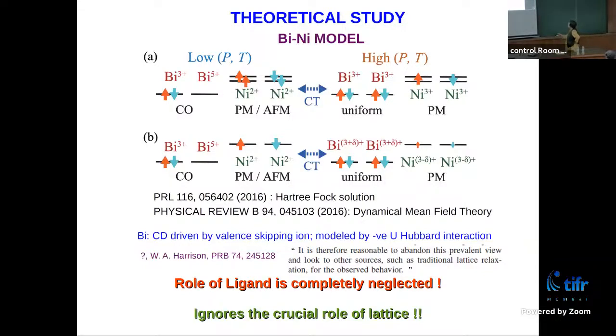And there was a famous concept, quite some time back, of the valence skipping ion, because bismuth is a valence skipping ion. It doesn't like to be 4+, and there was the concept of a negative U for this. And long back, Harrison said that modeling by this negative U is not a very comfortable thing, and you should instead bring in the lattice, which you have not considered at all. So we find that there are two major lacunae: the role of the ligand is completely neglected, and it ignores the crucial role of the lattice.